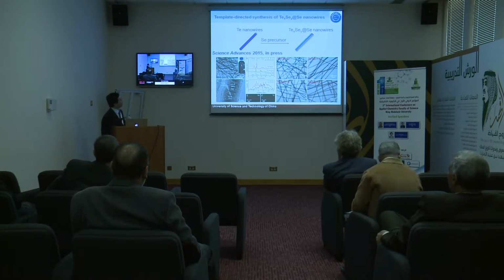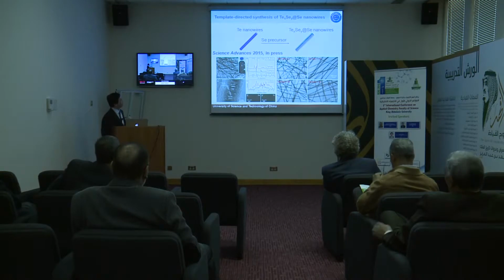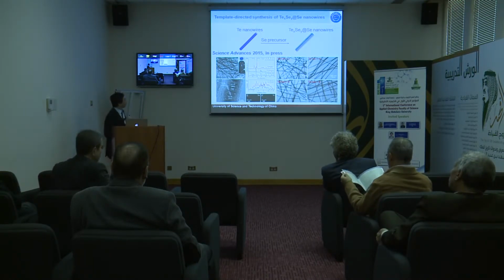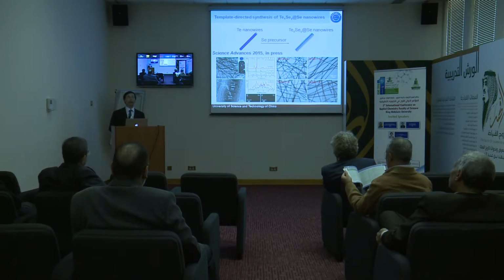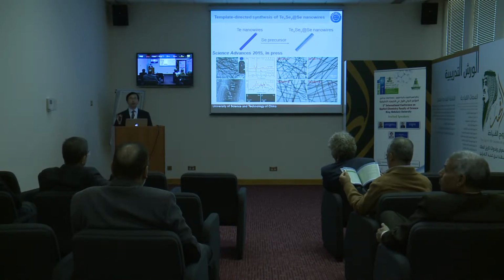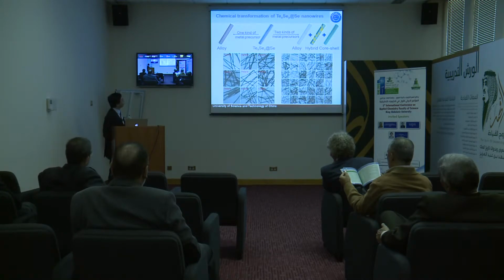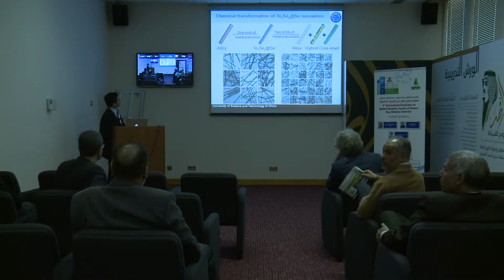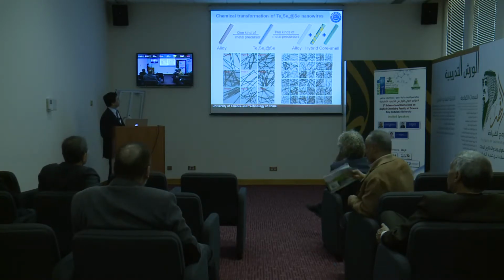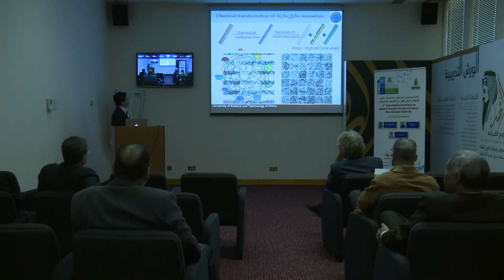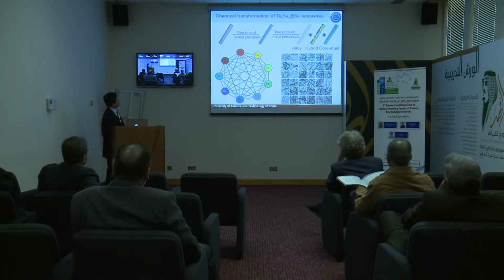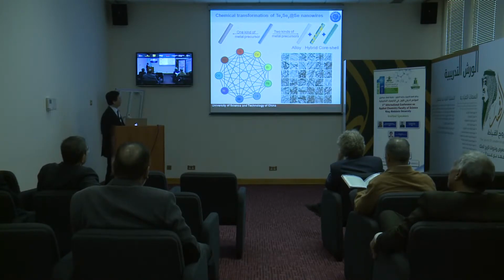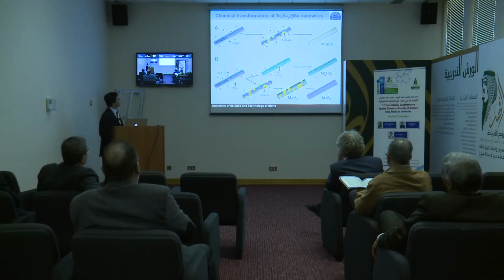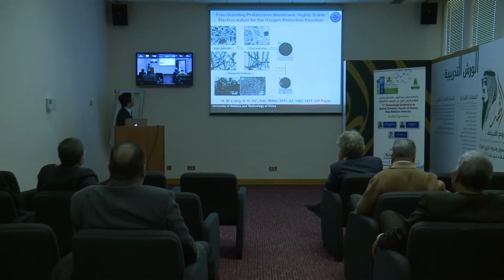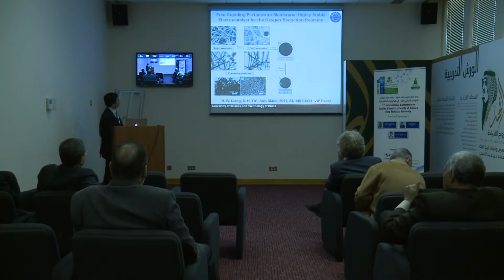Coupled with selenium elements, we find that this new nanostructure is also very reactive. They can react with many things, so that you can get different kinds of metal telluride, metal selenide, and also metal tellurium-selenium material nanowires in huge amounts, and in different systems. The good thing is that you can get nanowires with different composition of components. So now we can synthesize alloyed and hybrid core shell nanowires. I think it's more than 45 kinds of these inorganic nanowires with high quality. Due to time limitation, I don't have time to address more about the mechanism, but the synthesis is indeed highly efficient and very versatile.